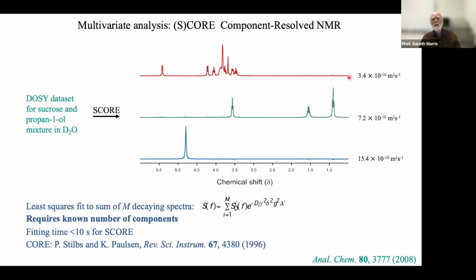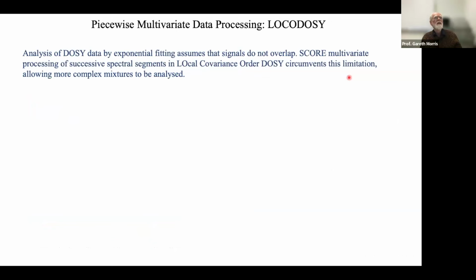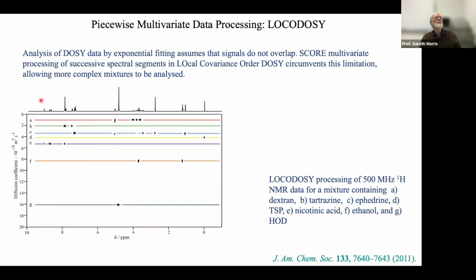But maybe if we were to divide our spectrum up into bits, what you might call a cut and stitch approach, then each small part of the spectrum could be treated to score analysis. And that's what we call the loco-DOSY or local DOSY method. The idea is that if we have a spectrum with many components in, if we analyze each small region of the spectrum separately and have only two or three components in each section, then we can reconstruct a very nice, fully resolved spectrum in which we manage to get all of the diffusion coefficients right and all of the spectra right.